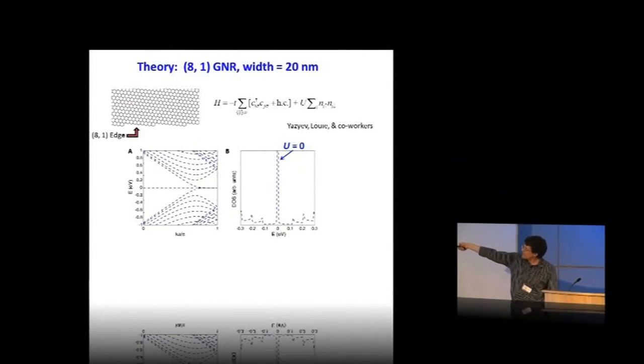So now we can start to compare our results to theoretical calculations. These calculations were done by Steven Louie and Oleg Yazyev and their coworkers, and they used a tight binding model to simulate the electronic structure of nanoribbons that have precisely the same symmetry, the same edge structure, and the same width as the nanoribbons that we measured. And here I show the results of their calculations. This is the electronic structure and the density of states that they calculated for this 8-1 nanoribbon with a 20 nanometer width.